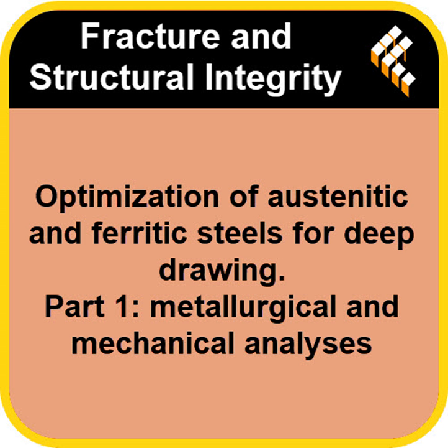Okay, massive difference. And the Erichsen test, the deep drawing simulation, did that confirm this? It absolutely did. The austenitic grades consistently got much higher Erichsen index values, the IE. So the standard 304 averaged over 13 millimeter deep draw. Well, the ferritic 430 only averaged about 9.5 millimeter. Big gap. What I find really interesting, though, is those modified grades. The 304 mod and the 441. They were specifically tweaked chemically for better drawing performance. Did that pay off?